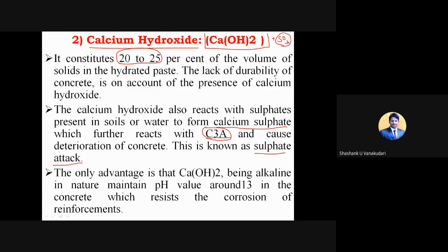The only advantage of this calcium hydroxide is being alkaline in nature and maintaining a pH value around 13. Alkaline is nothing but a pH value more than 7. So in the concrete it resists the corrosion of the reinforcement. Since we have used so many steel bars in the concrete, that iron content reacts with the water and forms corrosion. That can be reduced by this calcium hydroxide. That is the only advantage of the calcium hydroxide which is present in the cement.